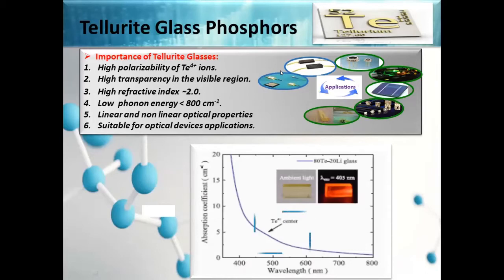We would like to have a phosphor which is transparent to light, so that the light emitted can come out. They have high refractive index, about 2, and phonon energy. The phonons are a hindrance. They are something undesirable in the phenomena of fluorescence because they give rise to non-radiative transitions. We would like to minimize them. So their phonon bands are only up to 800 centimeter inverse. Above that, there are no phonon bands.